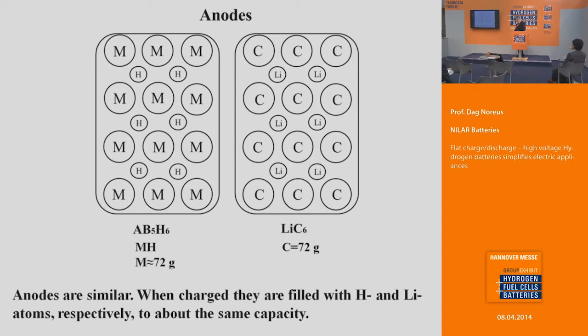If we look at the anodes first. In the anode of a metal hydride battery, you have a metal alloy, and hydrogen is stored in between. In a lithium battery, you have carbon, and lithium is stored in between. Average density is about the same here. You can use gaseous hydrogen in this. Then you have these satellite hydrogen batteries that are used in satellites, with the longest lifetime of all batteries. Hydrogen battery, we have gaseous hydrogen. So anodes are similar and charged with about the same capacity.